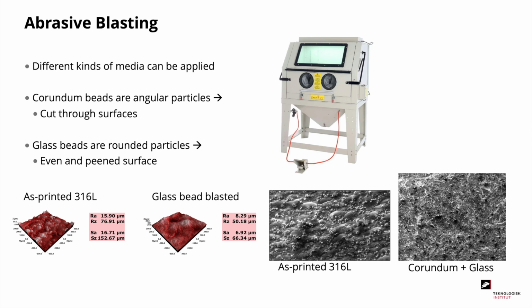After deburring we have abrasive blasting, and that can be done with different kinds of media. The two most common are corundum and glass bead. Corundum beads are angular particles which cut through the surface and remove some of the surface, while the glass beads are round particles and they make a more even and peened surface on the part. On the lower right corner you see an as-printed surface of, again, 316L stainless steel, and you see a surface that is blasted by corundum and glass bead, and again you see a more even surface compared to